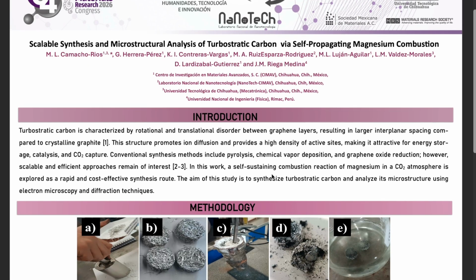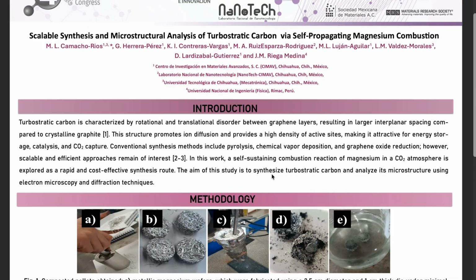To begin, let us contextualize the importance of turbostratic carbon. Unlike highly crystalline graphite, turbostratic carbon features rotational and translational disorder between its graphene layers. This structural disorder leads to an increased interplanar spacing. This is a key feature because it significantly facilitates ion diffusion and provides a high density of active sites. Consequently, turbostratic carbon is an exceptionally attractive candidate for energy storage devices, catalysis, and carbon dioxide capture.